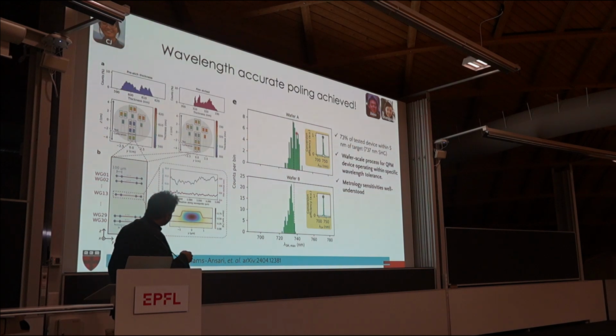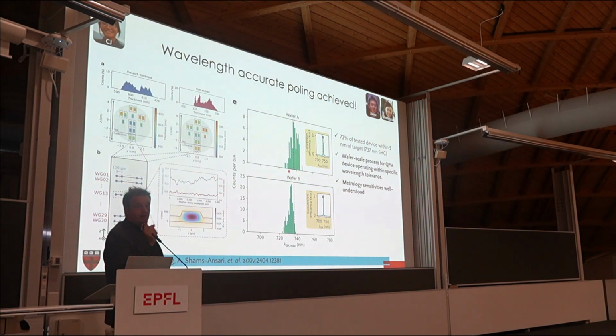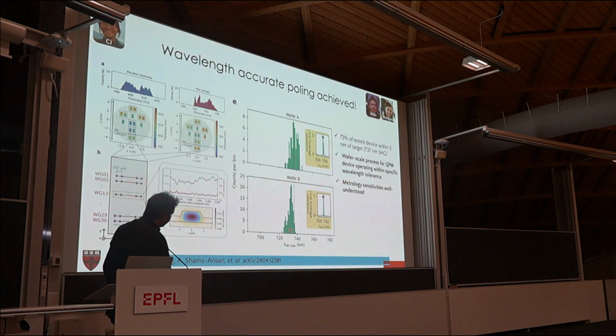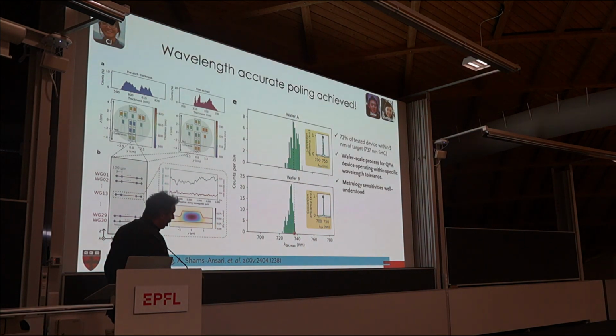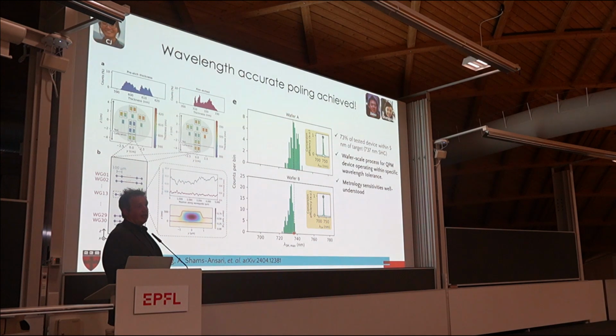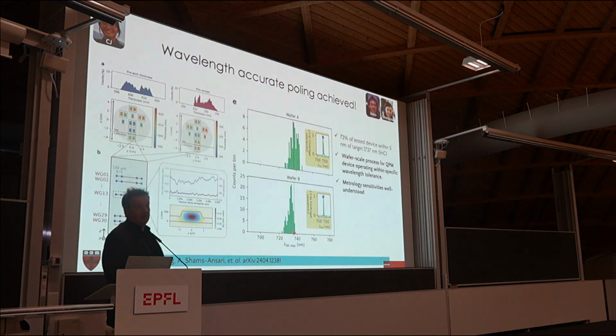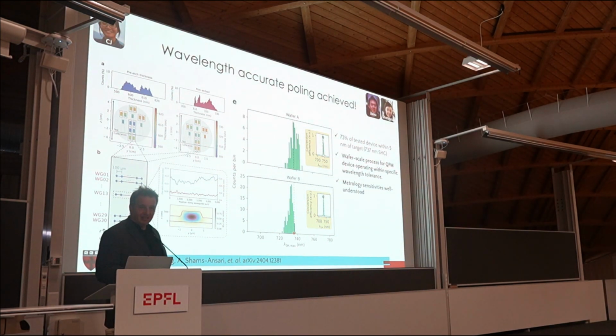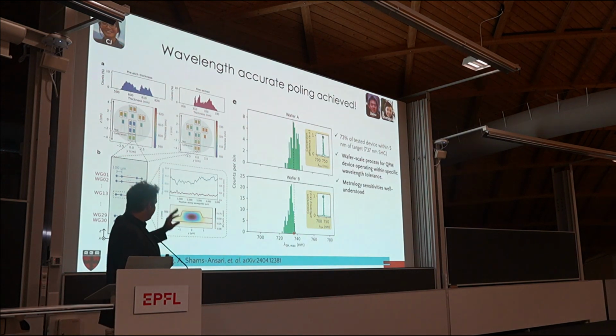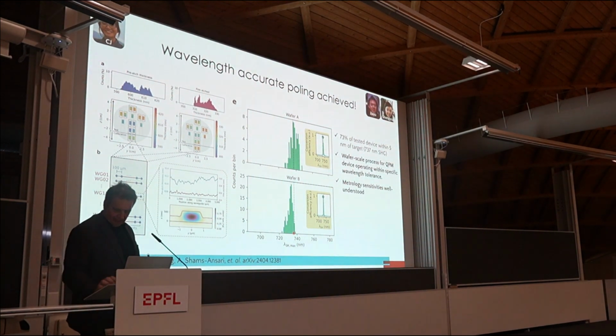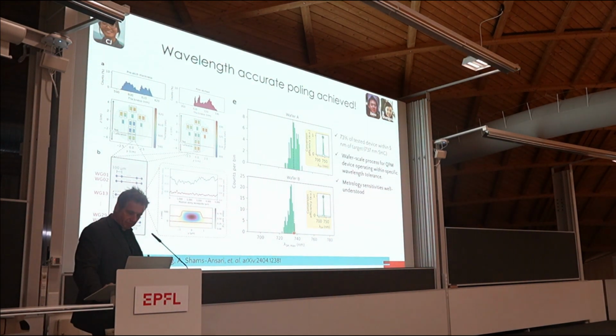Roughly, this is a histogram of devices on 2 different wafers that shows we get pretty close to 737 nanometers. Okay, we would like this to be a little tighter. We would like to be within the phase shifting range of a modulator. The reason why this one didn't work so well, even though it's a narrow distribution but it's off, is because we figured out that the ellipsometers in our clean room are not calibrated. We actually can use this process to calibrate the ellipsometer, which is not what I want to do. I would much rather have a better ellipsometer and be able to measure the thickness precisely. But it just tells you how sensitive this process is. So I'm really excited to see that also here at EPFL there's a lot of work, at CSEM and EPFL, actually going in this direction.